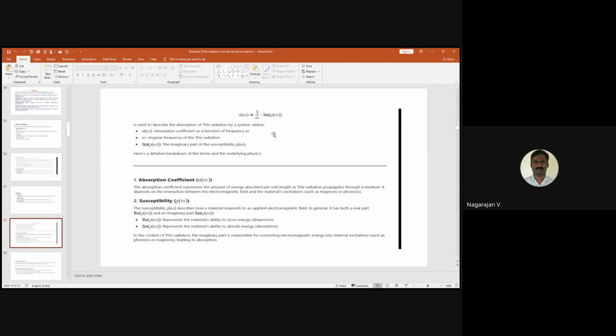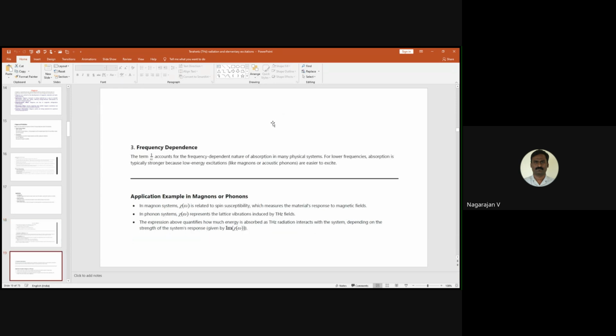In the context of Terahertz radiation, the imaginary part is responsible for converting electromagnetic energy into internal excitations, such as phonons or magnons, leading to absorption. And for the frequency dependence, the term 1 by omega accounts for the frequency-dependent nature of absorption in many physical systems. For lower frequencies, absorption is typically stronger because low-energy excitations like magnons or acoustic phonons are easier to excite. The magnon system is related to spin susceptibility, which measures the material's response to a magnetic field.